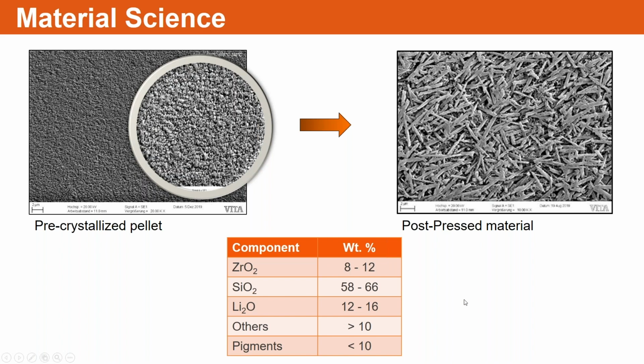But what VITA discovered was that with this material, lithium disilicate, at least with our composition, after you press it, there is a way that you can temper this. We used to do this in the old days for metals. We used to cast it, and then we would let it cool, work with it, and then we put it back in the oven, and we would temper it to realign some of the grains, to condense them, to make them much stronger. We found that true with our lithium disilicate material.